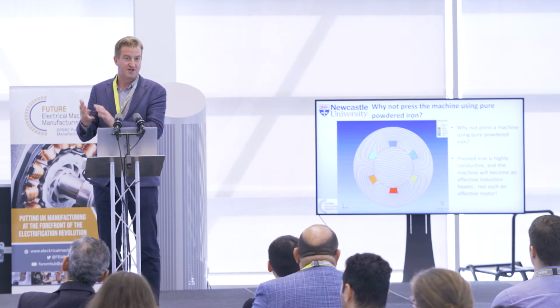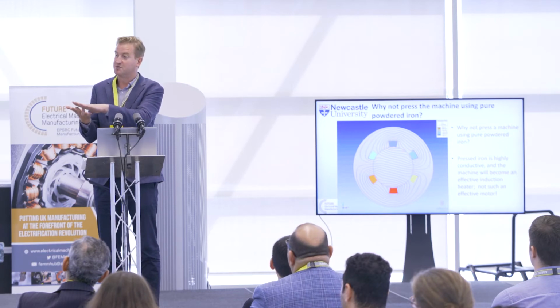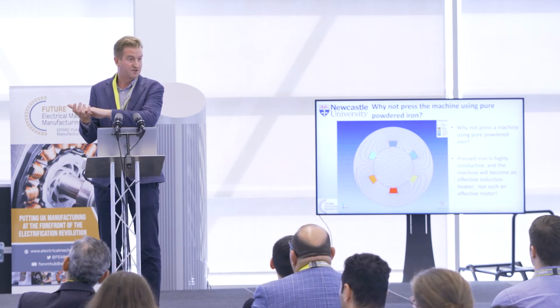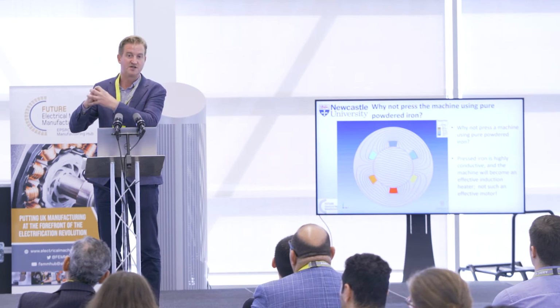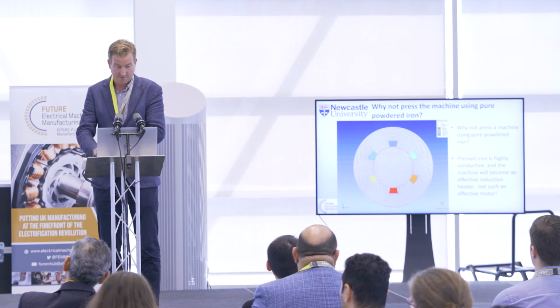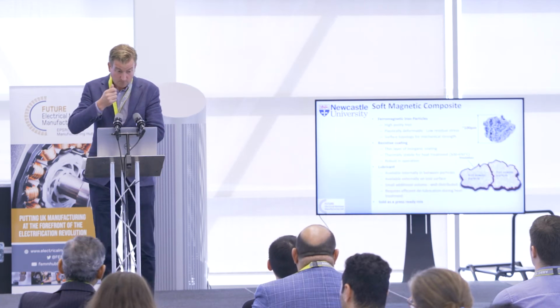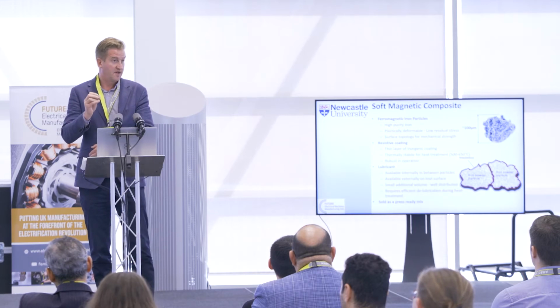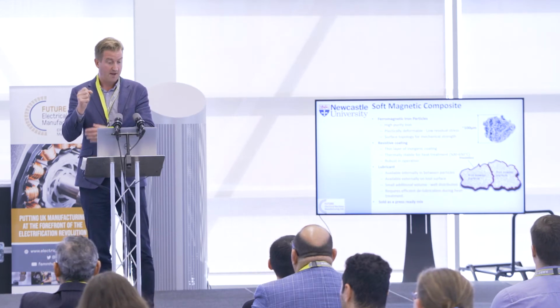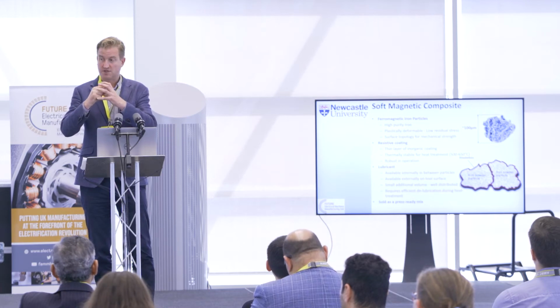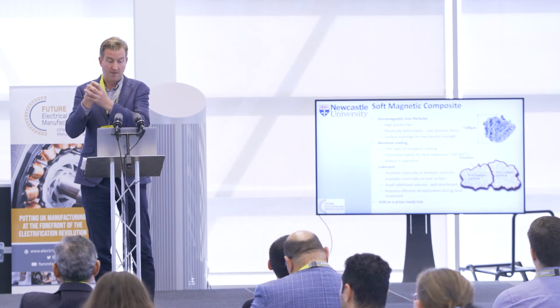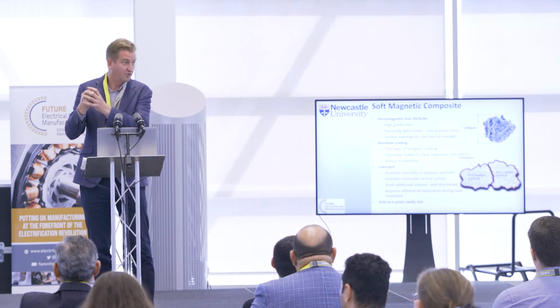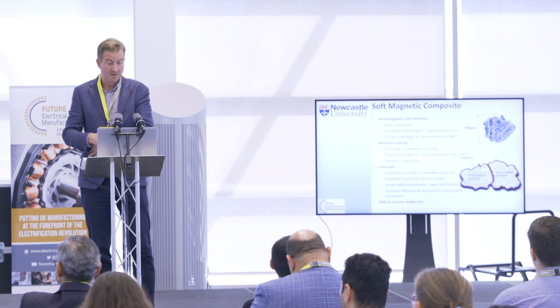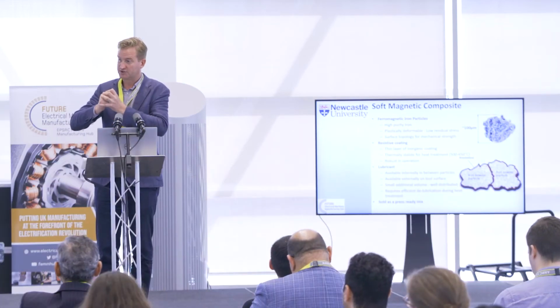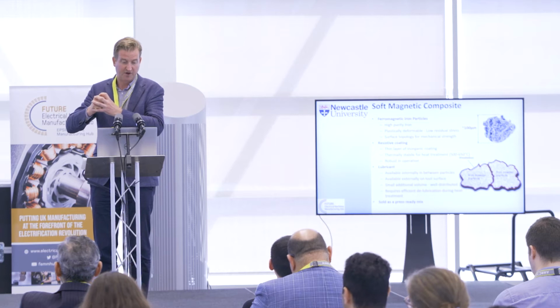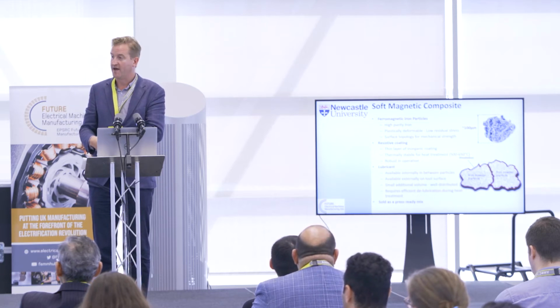So we need insulation. The laminations do the job of that. We've got the insulation between the layers. With soft magnetic composite, we've got to have the insulation on each of the particles of iron powder. So soft magnetic composite is high purity iron powder, made using a water atomization process, and it's 100 micrometers or smaller, depending on the grade of the powder. It's deformable, so when we squash it, it does change shape and it does interlock itself. And there are various surface coatings on there.